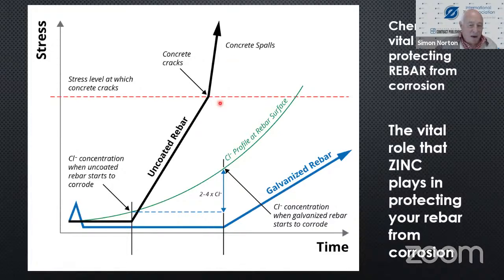it spalls. However, if you galvanize, because chlorides attack zinc, zinc goes into solution, it lets go of 2 electrons, and you get the formation of zinc chloride. So you get a formation reaction, a reaction happening between zinc and chlorides, and chlorides are very bad for galvanizing. However, if you galvanize, you will essentially withstand the effect of chlorides, and you can stand a higher concentration. Only at this point does corrosion start to take place. Your galvanized rebar only starts to show internal stresses over here, and hence you've protected it.